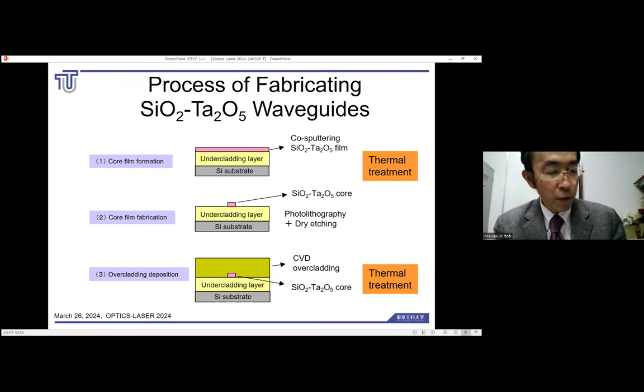This is the process of fabricating silicon dioxide, tantalum pentoxide waveguides. First, undercladding is deposited on a silicon substrate, and silicon dioxide, tantalum pentoxide thin films are deposited by co-sputtering. Then, heat treatment is performed to densify and improve the quality of the quartz glass. Next, the core is processed through photolithography and dry etching. Finally, an overcladding is deposited using the CVD, chemical vapor deposition method, to embed the core, followed by heat treatment.